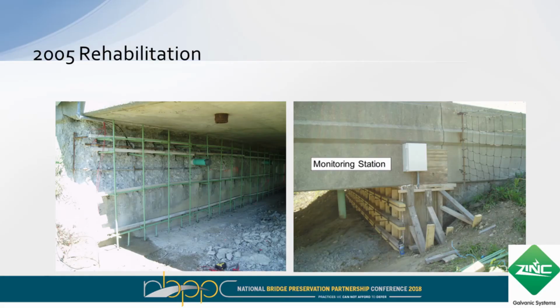New reinforcing steel is placed, the form was placed, self-consolidating concrete was used to build out the wall, and that was monitored. That was in 2005, and those are continuing to perform very well. This is 10-year data on that. We saw a little bit about metallizing. Metallizing is also used on concrete for cathodic protection purposes. This is showing a zinc metallizing option.